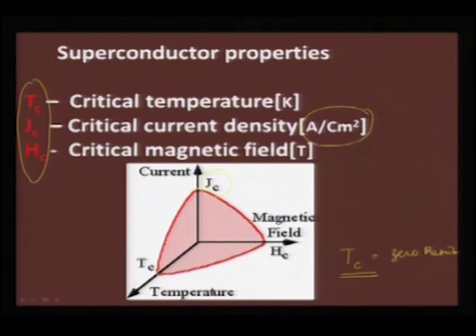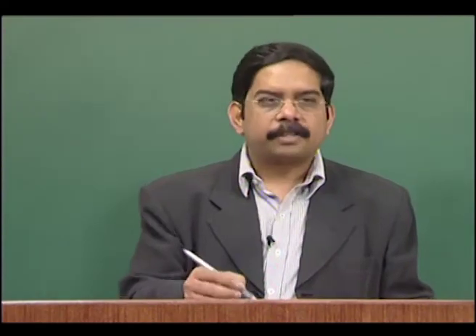And then the critical magnetic field is another issue, where the material can sustain only a particular amount of magnetic field, beyond which the flux density of the applied field can go into the compound. In other words, it will remove that diamagnetic state. So, when the compound can repel that particular amount of field, that is called the critical magnetic field, and that is the strength of your superconductor, the diamagnetic state. So, all these 3 have to be measured.